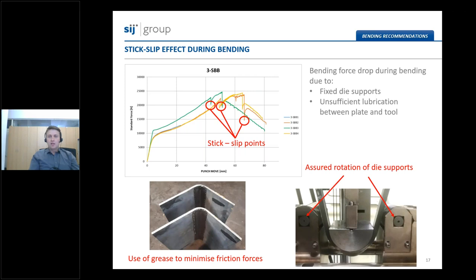We have to explain a little bit the stick slip effect. What is actually the stick slip effect? It is an unwanted phenomenon during the bending procedure. So for better explanation, we will take a look at the following diagram, where the bending force during the punch move is shown. We measured the forces during the bending operation on some of our plates. As you see in those red circles, there are sudden drops of the bending forces. This is, I think, a much more frequent phenomenon at higher bending forces.